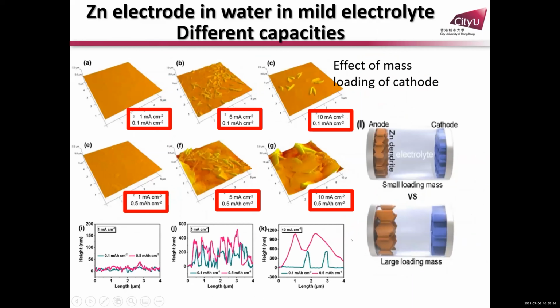If you go further, even at the same current density, 5 for example, if you go for different areal capacity from 0.1 to 0.5, you see the dendrites are totally different. That means at different capacity you see different dendrite behavior. High capacity means high loading mass of cathode, and with high capacity you have even more severe dendrite growth. So this study tells us we cannot directly say whether there are dendrites for zinc batteries. It can have dendrites, it can have none. It depends on the testing condition.